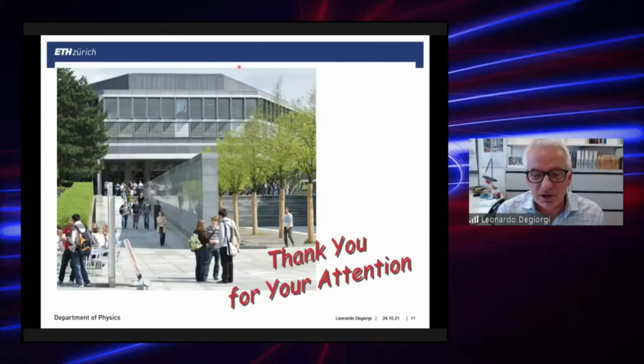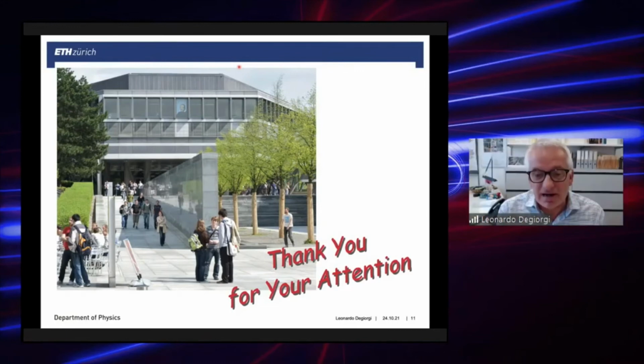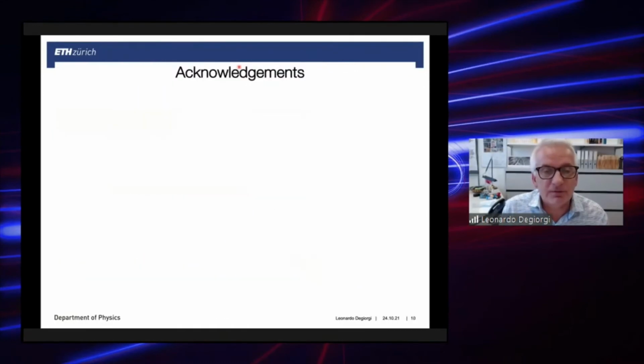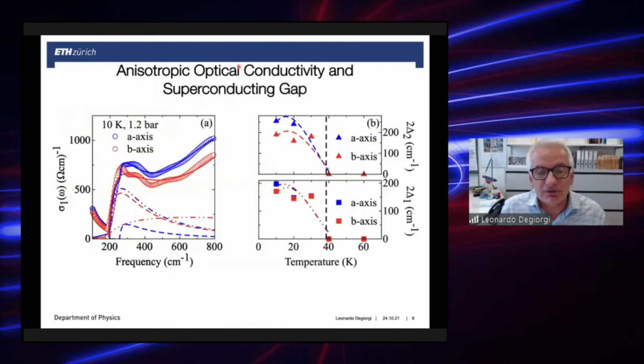We do have an electron-phonon type of anisotropy, but actually the anisotropy that I show you, maybe I can go back to this view graph, that I show you here in the optical conductivity. Actually, what it does imply is an anisotropy in the suppressed spectral weight because of the opening of the superconducting state. And this suppressed spectral weight actually moves in the collective mode, which we cannot obviously measure directly in our experiment, of the superconducting state itself. And this should imply actually an anisotropy in, how can I say, the penetration depth,